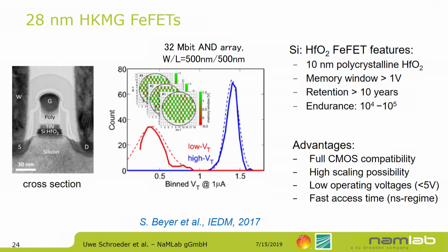So overall, from the FeFET's feature point of view, we have polycrystalline hafnium oxide, a memory window of 1 volt, retention larger than 10 years, and endurance on the order of 10^4 to 10^5 cycles. And then again, similar to what I showed for the capacitor case, you get charge injection into your interfacial layer, and this charge injection would shift your threshold voltage so that the memory window closes. So the device doesn't break, it's just a shift, and you can detrap your device and it would work again. The overall advantages: it's fully CMOS compatible and highly scalable. Compared to your USB stick, where you need like 18 volts, here you're in the 5 volt range, so you have a much lower voltage you apply for switching, and you have fast access time.